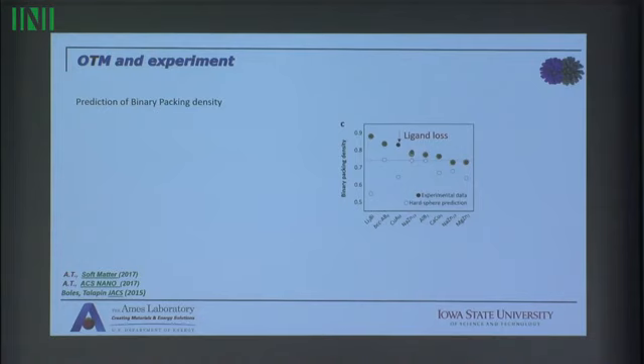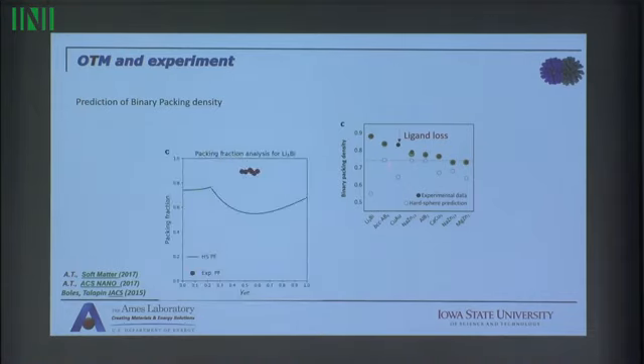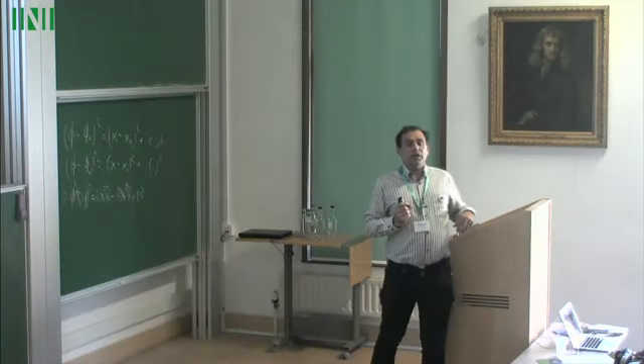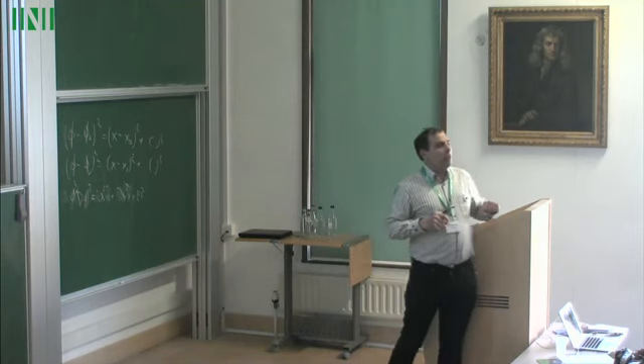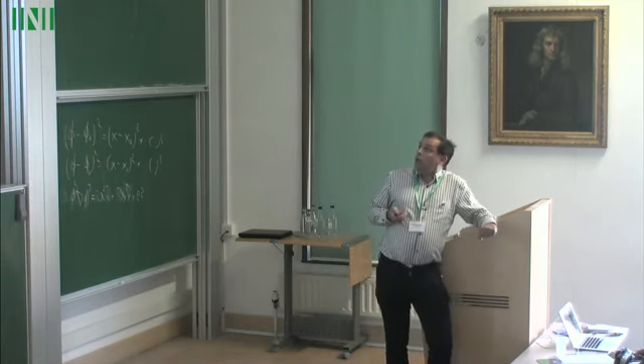And there is one case which we couldn't predict, but it actually has to do with a different type of bonding that occurs. For example, here you had the lithium-3 bismuth that I mentioned before. Now it turns out that when you do the right thing, you see that there is a new branch, and the experiments, once again, fall perfectly within what we predicted. So with this description of nanocrystals as soft skyrmions, and vortex textures appearing in the particular circumstance we described, without any fitting parameter or any free parameter, we are able to explain all experimental systems.